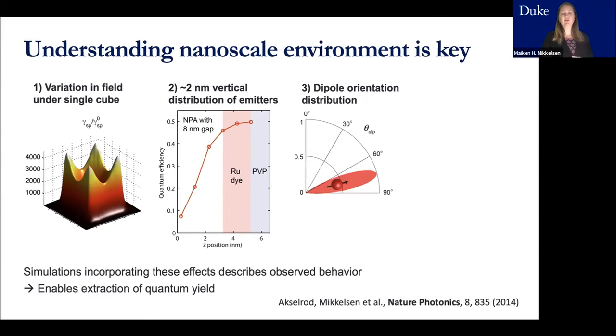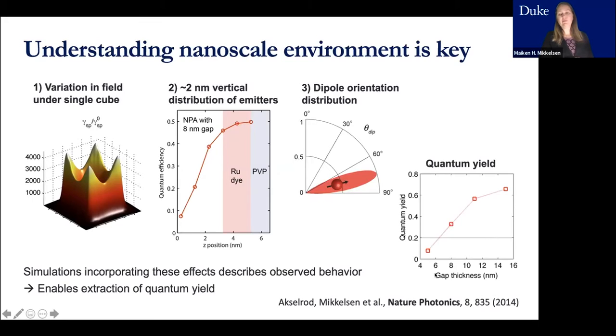When we take all these things into account, it describes the experimentally observed behavior very well. It allows us to extract the quantum yield here as a function of the gap thickness. And we can see that as we go to small gap thicknesses, the non-radiative rates are increasing significantly, as expected.